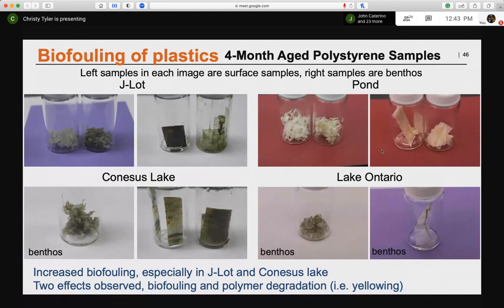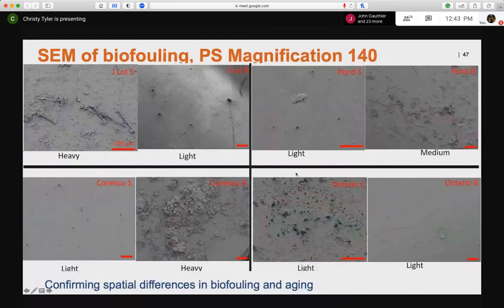And then, like I said, we're also looking at what's happening to the chemistry. To also look at the morphology, we've taken high magnification SEM, scanning electron microscopy, of these different samples as well. Again, we're still looking at the polystyrene, and for SEM, we've taken much higher magnification as well. You see the same type of ideas, and this is really confirming the same spatial differences of the biofouling.